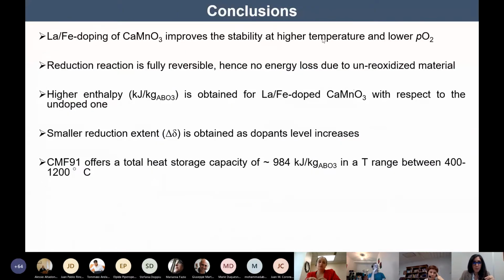So in conclusion, I would like to say that the doping is fundamental for improving the stability of the materials, and it can be easily used for tuning the thermochemical properties of the materials, starting from the enthalpy up to the reaction extent. And we identified this material, the CMF91, that offers a good heat storage capacity of 984 kilojoule per kilogram, and it operates in a very broad temperature range, that is 400 to 1200 degrees C.